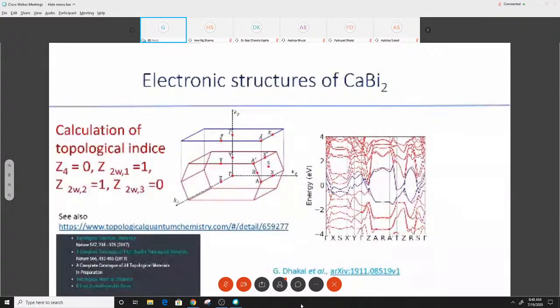On the left side, we saw the conventional Brillouin zone for calcium bismuth, and we have noted the high symmetry points, and the blue color structure shows the 2D projection of the 3D Brillouin zone. And on the right side, we saw the bulk band calculation of calcium bismuth, and in that one, we can see some bands are crossing the Fermi level. That indicates this sample is metallic. However, there is a band gap between these two blue bands, which indicates that on the basis of the band calculation, it equally can be taken as an insulator.